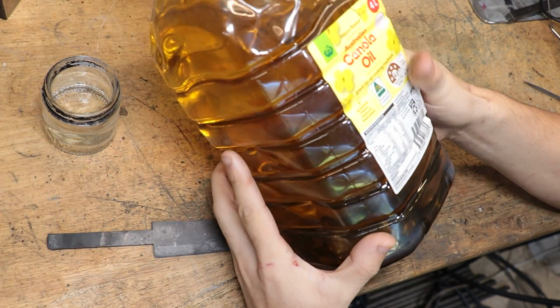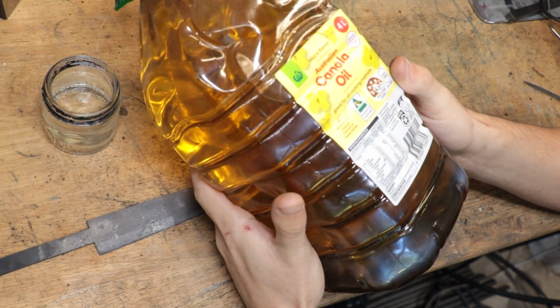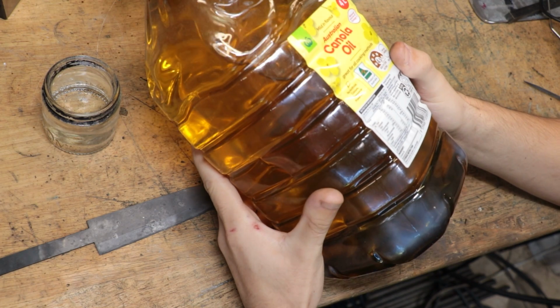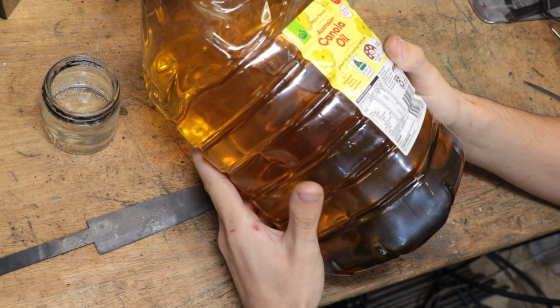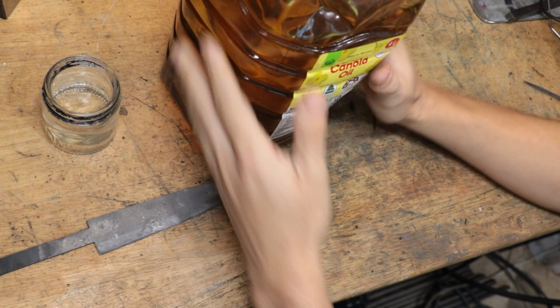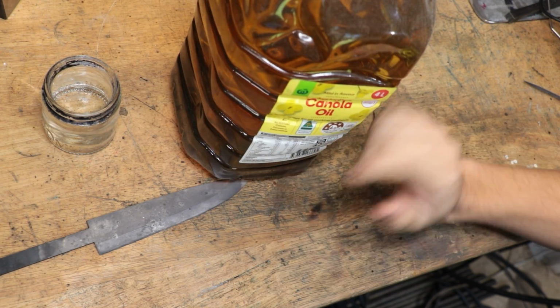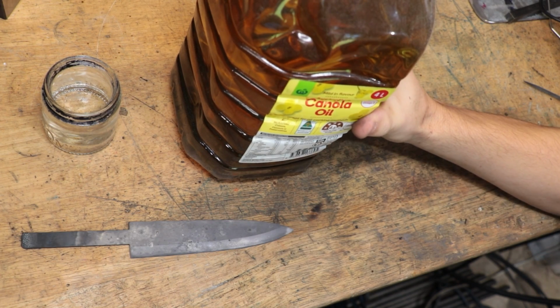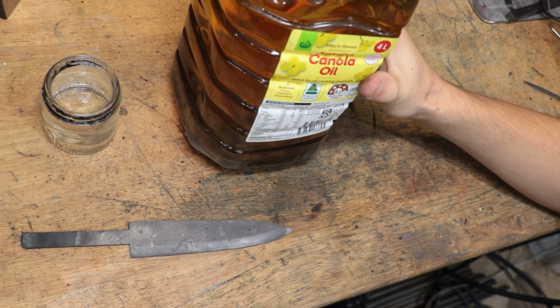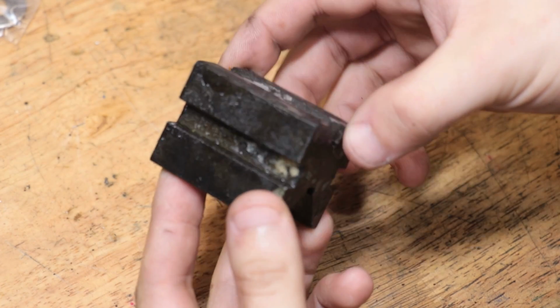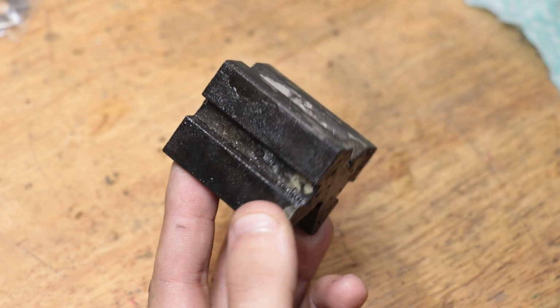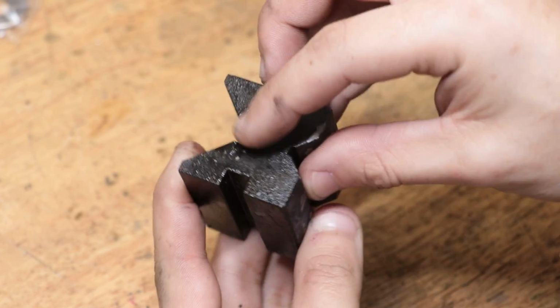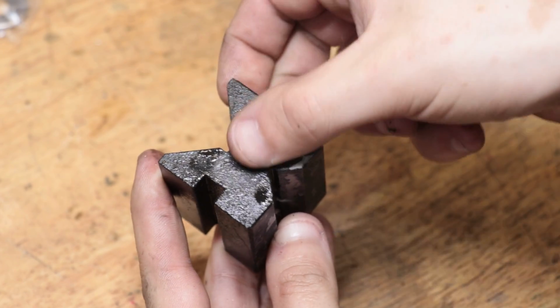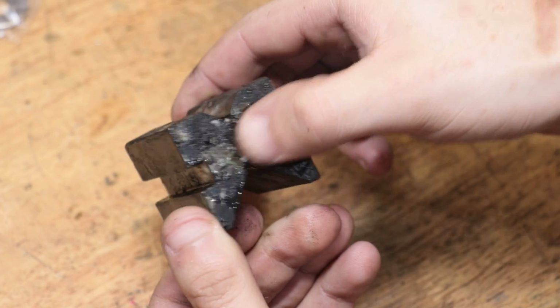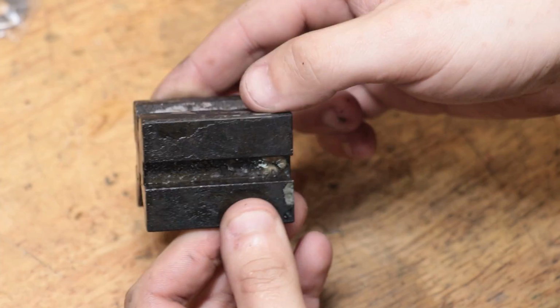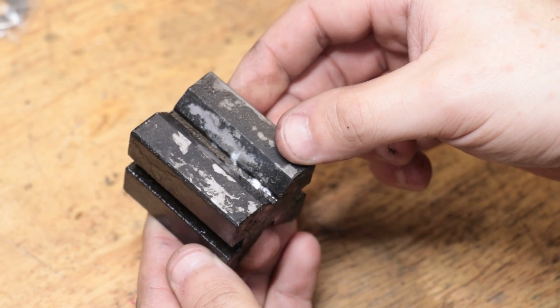Now, there are special quenching oils with specified cooling rates that they do sell, but for home shop use, I've always used vegetable oil and it works just fine. Most oils tend to cool at a very similar rate, and for home workshop use, you really aren't going to notice the difference. The only big downside to using oil is the cleanup and the residue that's left on the part. It's polymerized oil, which is very similar to seasoning a carbon steel wok, but it can be a nightmare to remove. Sodium hydroxide tends to help break it down, and then steel wool helps remove the rest.